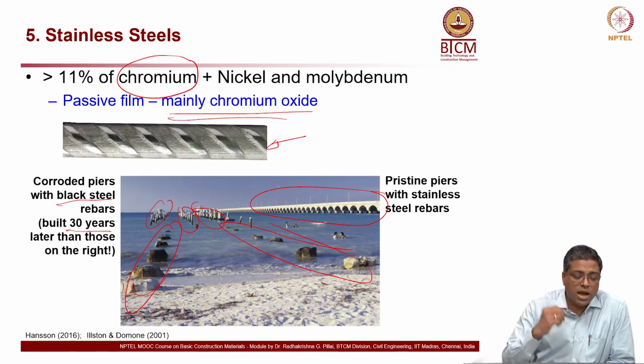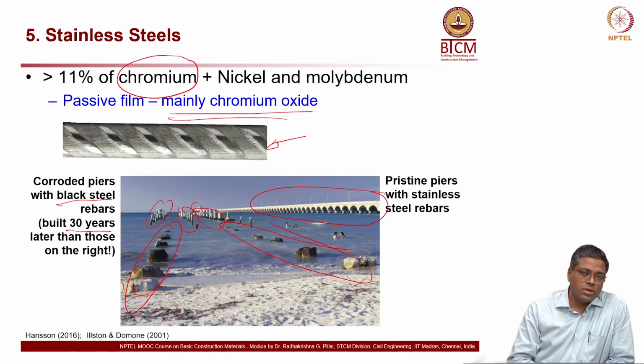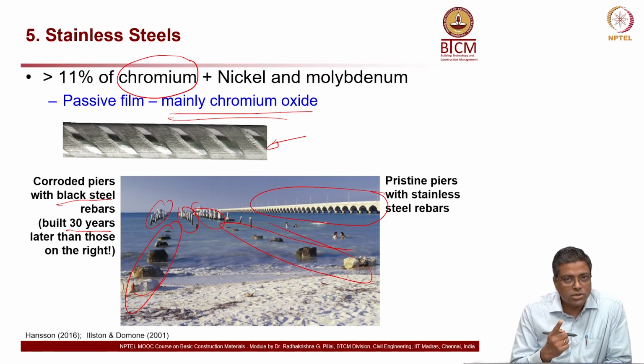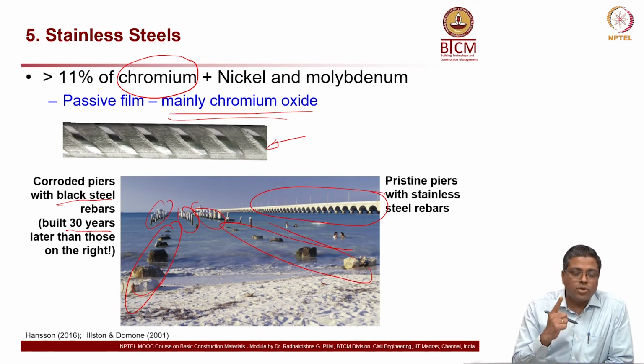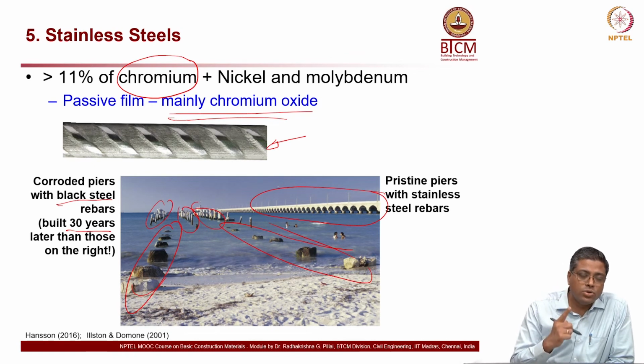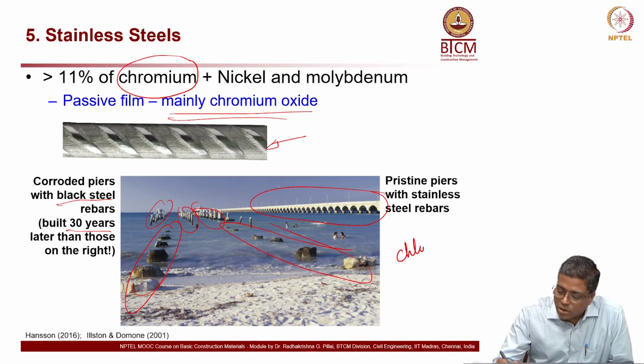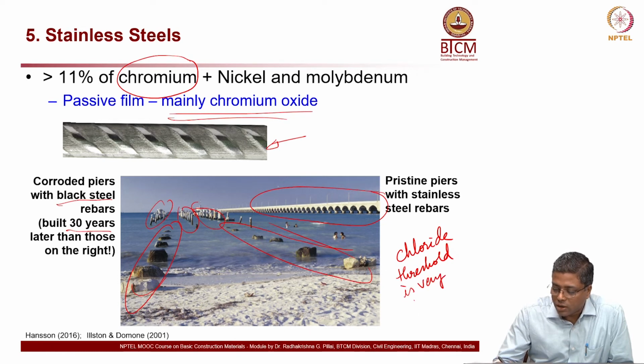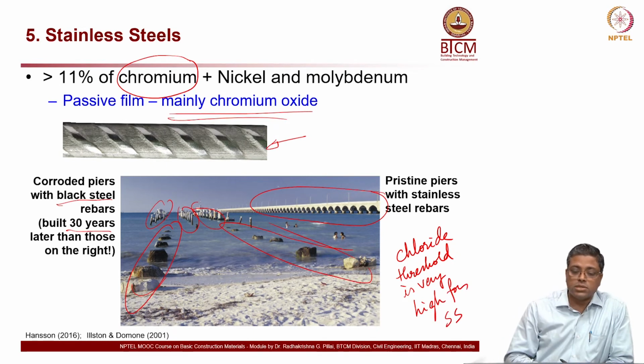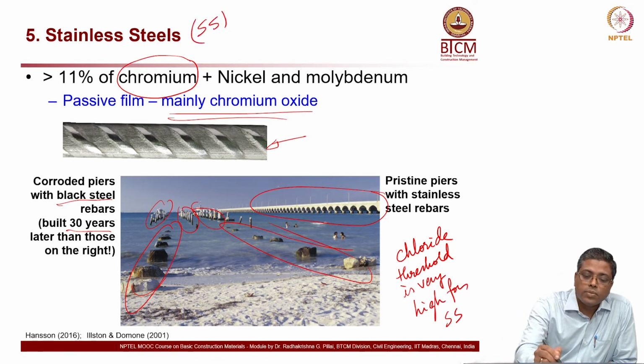So it has a very high chloride threshold compared to regular steel. What is chloride threshold? It's the amount of chloride which is required to initiate corrosion of the steel. For stainless steel, you need much more chlorides than for regular steel. Let me write that terminology here. Chloride threshold is very high for SS, or stainless steel.